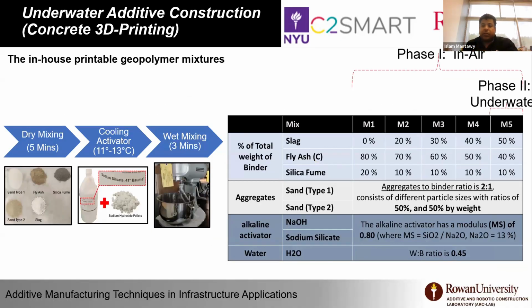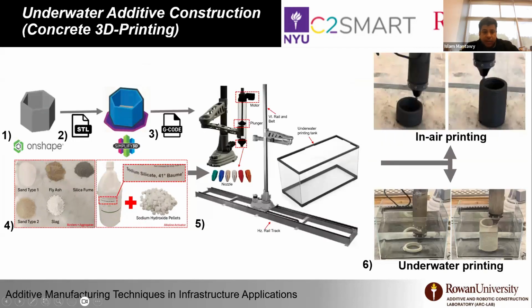We came up with really different designs for mixes that can be printable. As you can see here, for the mix design, we did two phases. One is called in-air printing. We published a paper on it, and we have papers now under review for phase 2, which we did for underwater. So basically, the printing process is the same with a different material, but this material really sets fast. It's still one-component, but the chemical activator enables fast chemical reaction and solidification.